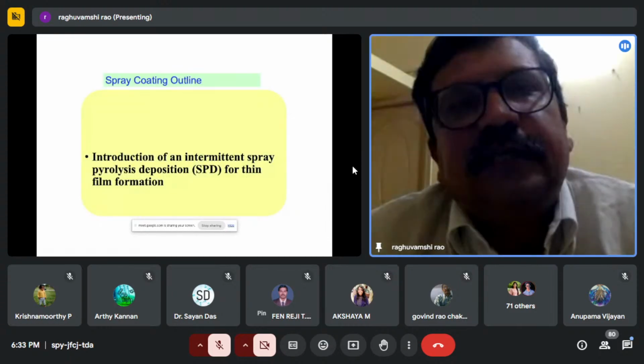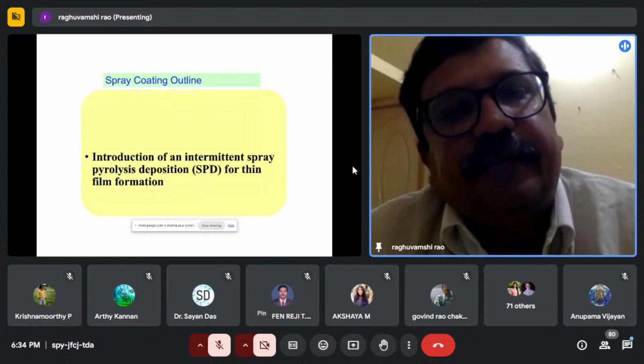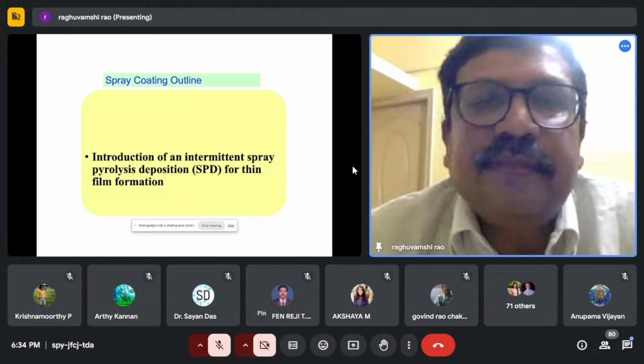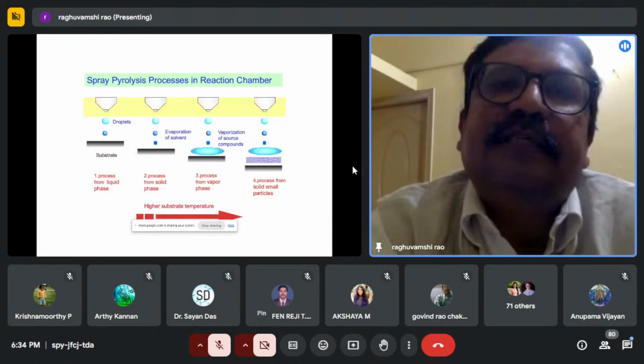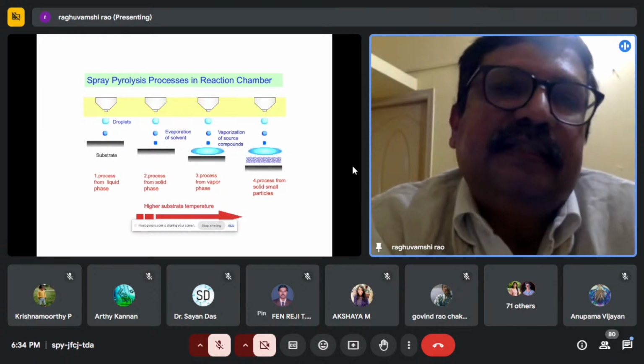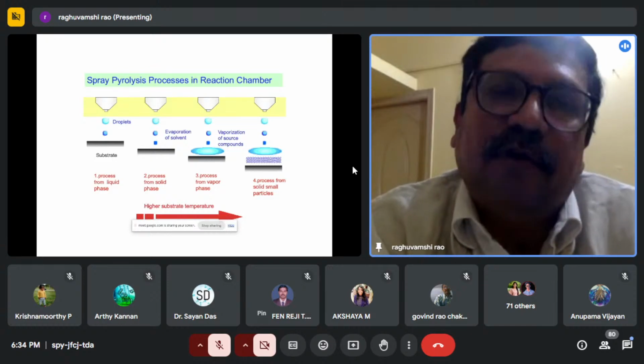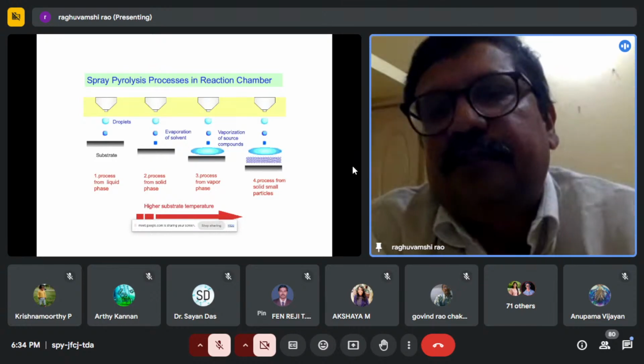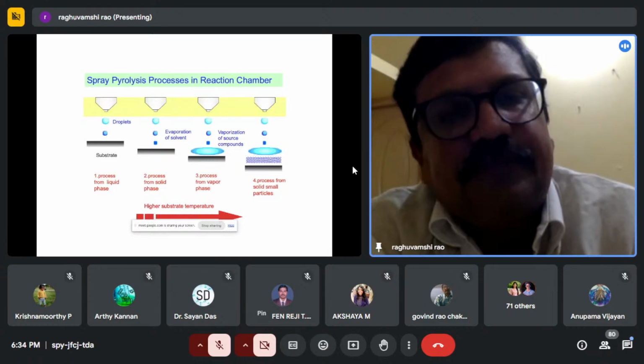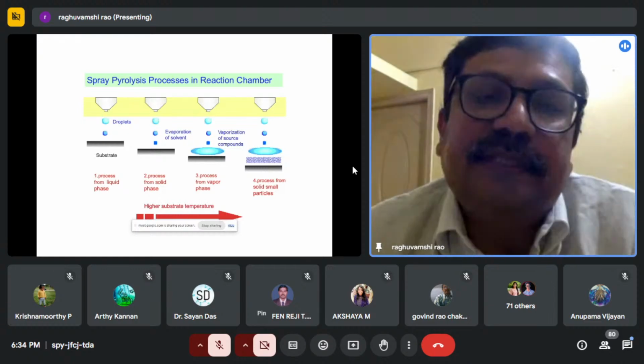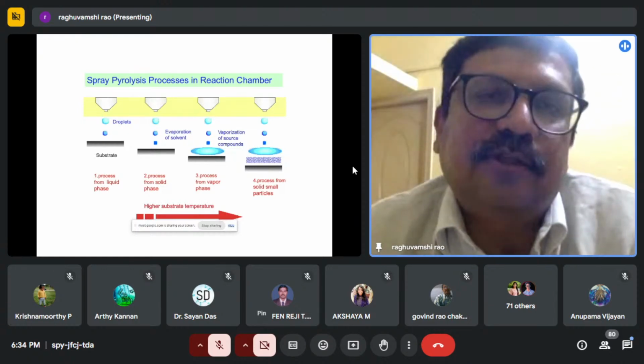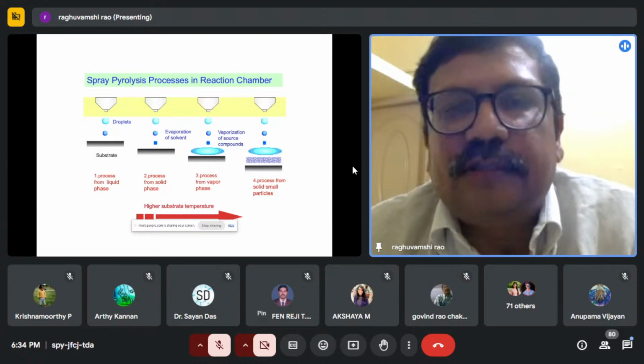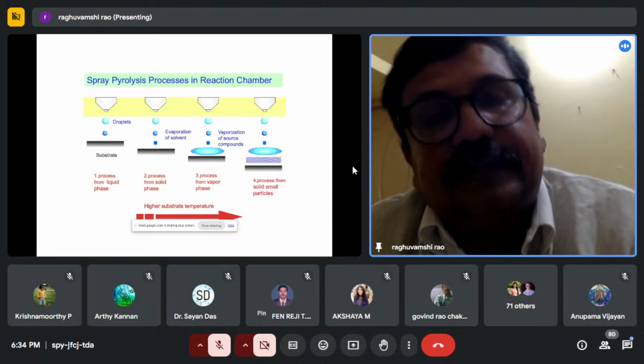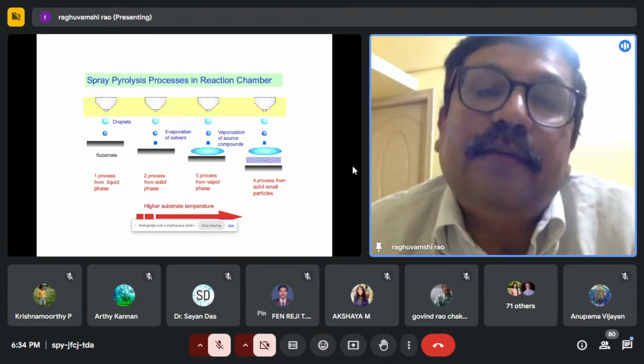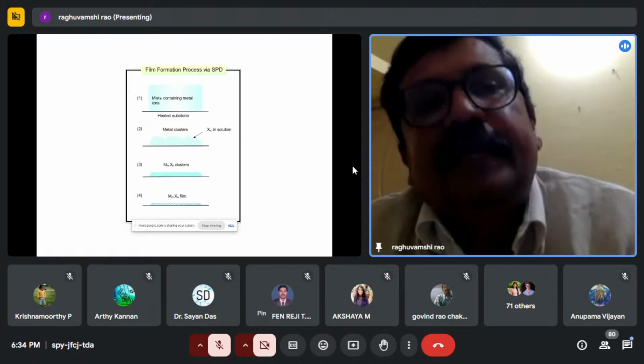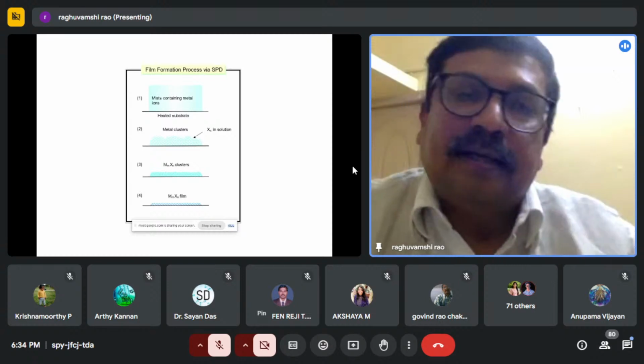I would like to throw some light on the spray coating also, an introduction to the intermittent spray pyrolysis deposition system for thin film formation. Spray pyrolysis process in the reaction chamber is primarily understanding the droplets which fall on the substrate, evaporation of the solvents and vaporization, and finally the deposition of small particles on the substrate. It works at higher substrate temperature, between 300 to 600 depending upon the solvents that we apply here. It's intermittent because after every spray falls on the substrate, there could be a temperature drop. So we give time for the substrate to regain the required temperature, again to have the complete particles inside the system.